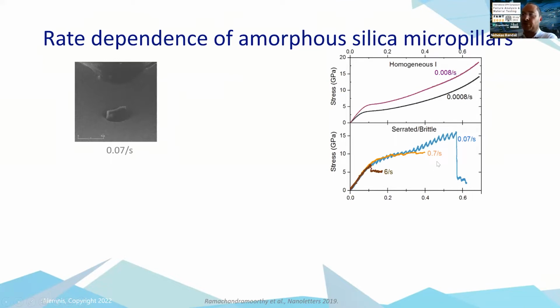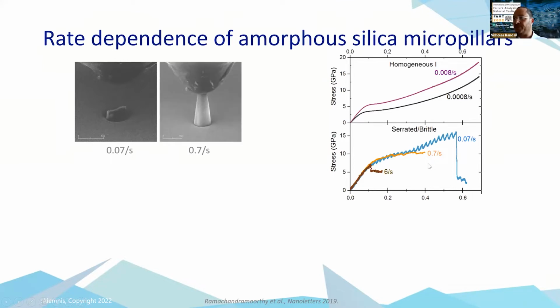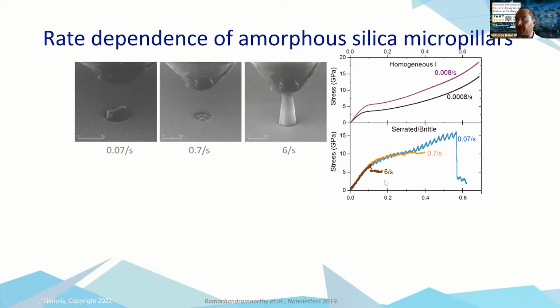If we go to the next order of magnitude, 0.7, now we're very brittle, and we see that in the data. So we break more quickly, and there's very little ductility. If we go to the next order of magnitude, 6 per second, now we're still brittle. This is the most brittle state, and there's no ductility at all, pretty much. So we might assume that if we go faster, we might become even more brittle, because if you hit a piece of glass with a hammer, it smashes, right? You don't get any ductility coming back.